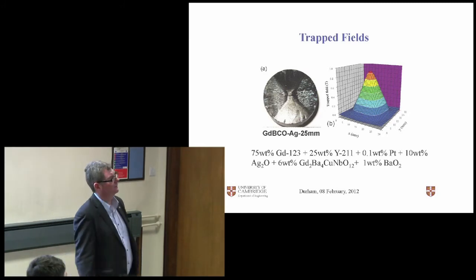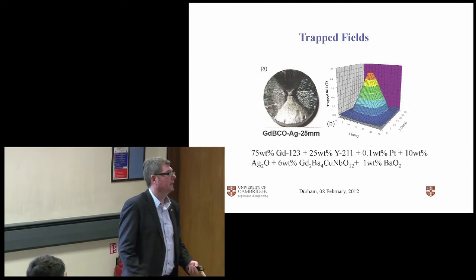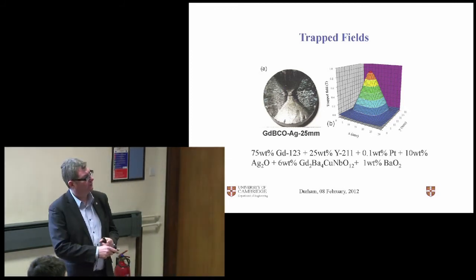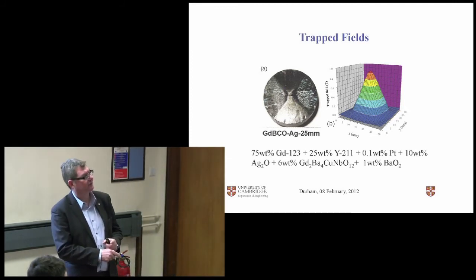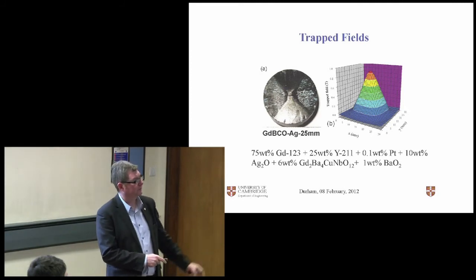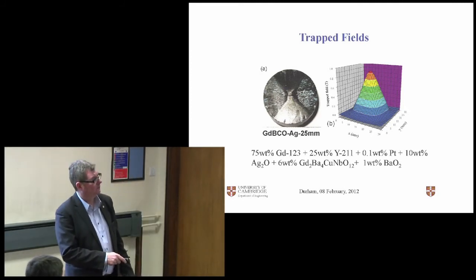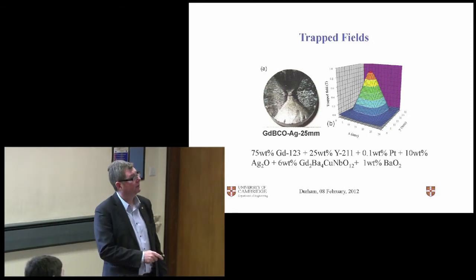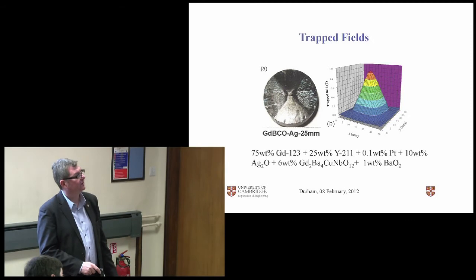So after all that, what trap field do you get? Well, in theory, the bigger the sample, the bigger the trap field. So this is a gadolinium barium copper oxide sample, the one that I've just described. It contains the 211 phase. It's only 25 millimeters diameter, and we're getting a trap field of more than a Tesla.